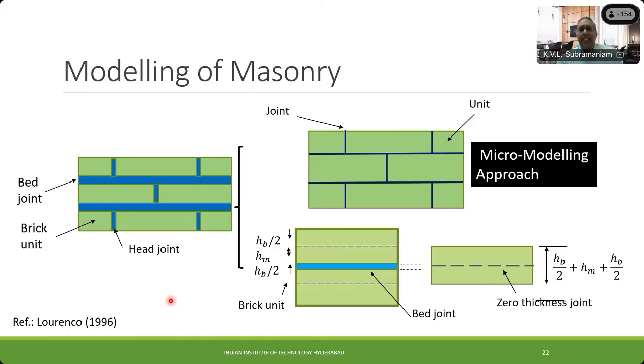So now I'll quickly run through the modeling of this. With this data, we developed a material model, which is also called the micro model, or micro approach. If you have a masonry assembly like this, you basically assume that the mortar interfaces are infinitesimally thin. Basically, you expand the bricks so that the mortar interface essentially disappears and becomes infinitesimally thin. This is now called a joint.